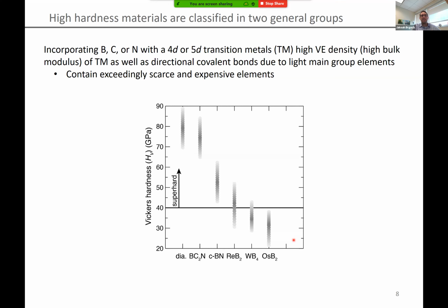And so combining this high valence electron density with the short covalent bonds stemming from the boron, the carbon, the nitrogen, is in fact why we get these really impressive mechanical properties.